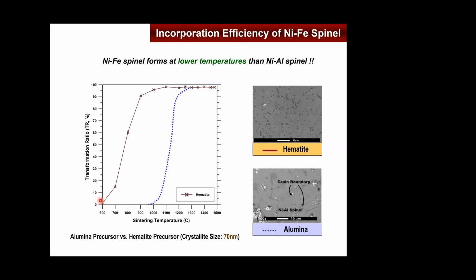So we also tried iron, and the news was even more exciting. If you compare to the alumina system, the iron system can pretty much stabilize nickel at probably 200 to 300 degrees Celsius less. That explains a very important scenario: when you take natural clay or soil, mix it with your heavy metal materials and heavy metal sludge, and burn it at relatively high temperature, the iron will actually step out first to stabilize your nickel, your heavy metal. And once you exhaust the nickel, then they go for alumina at relatively high temperature.